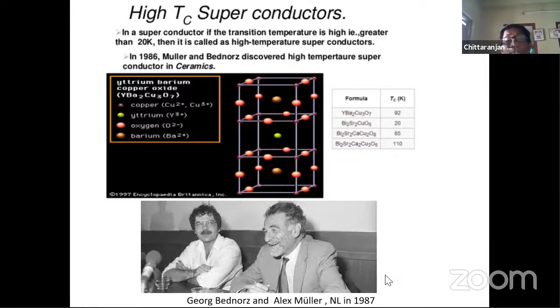Followed by this, there were many developments throughout the globe for superconducting materials. But surprisingly, the material developed by Bednorz and Müller in 1986, for which they received the Nobel Prize the next year in 1987, is a very simple molecule: yttrium barium copper oxide. A high temperature superconductor, its critical temperature is much higher, around 92 Kelvin. This type of mixed metal oxide may be stoichiometric or non-stoichiometric, and in the non-stoichiometric case the conductivity is much higher. The structural demand of these materials surprisingly regulates the conductivity.